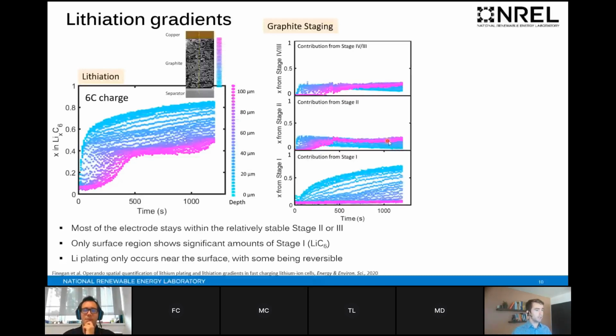And so this will have consequences for lithium plating as well. As you reach stage 1, that means we can no longer lithiate beyond that point. So the local overpotential to drive current is expected to spike up around the surface areas, around the separator. And that overpotential is very likely to exceed the 0 volts that I mentioned before and end up having favorable local conditions for lithium plating.